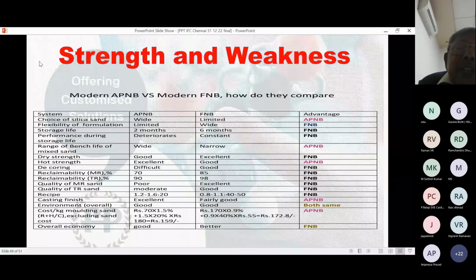Reclaimability by mechanical is 70 to 85% in Alphaset, 85% in Furan. Reclaimability by thermal is 90% for Alphaset and 98% for Furan. Quality of mechanically cleaned sand is poor in the case of Alphaset, and moderate in the case of Furan. Recipe or use level is 1.2 to 1.6% resin to 20 in the case of Alphaset. It is 0.8 to 1.1% to 40 to 50 in Furan. Casting finish is excellent for Alphaset. It's fairly good for Furan.